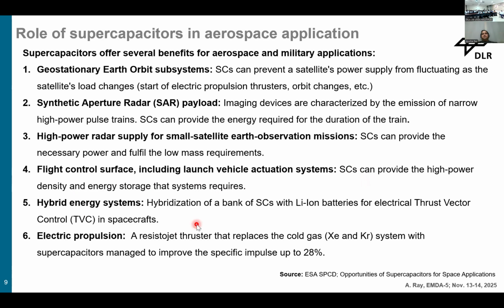in current aerospace research, they are trying to combine the supercapacitor and lithium batteries or different batteries to make a hybrid energy pack, an energy bank that can fulfill our needs. When we need high power density or high power, the supercapacitor can work, and where we need high energy, lithium batteries can work. But overall, the weight of the energy pack can be reduced even up to 50 to 70%. And with electric propulsion, this thruster replacing the cold gas thrusters, the supercapacitor managed to improve the specific impulse up to 28 to 30%.